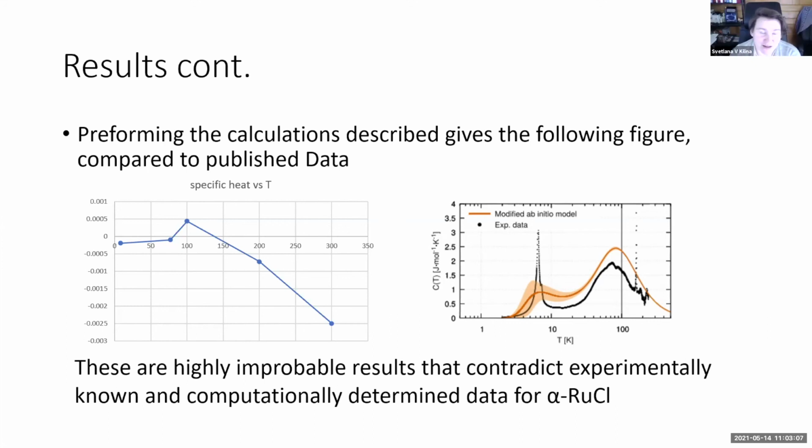Please explain. One of the leading theories of what causes that large spike you see at about 8 Kelvin in the experimental data is that there is an interaction that arises from the off-diagonal components of the electron density, and that by using a collinear method, we ignore that and treat it as non-existent. And so that would obviously dramatically impact the results.